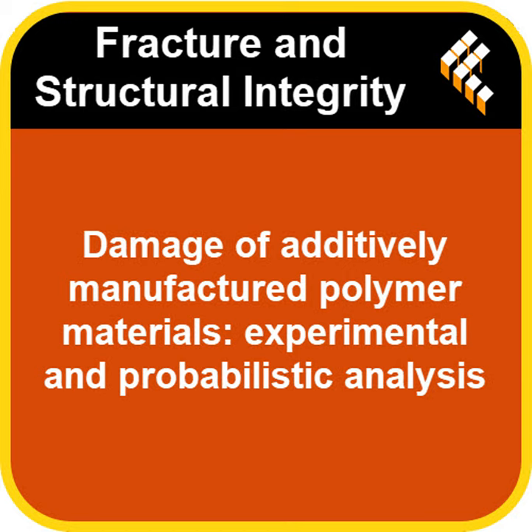And this study's results on PLA really drive that home. They tested orientations at 0 degrees, 45 degrees, and 90 degrees relative to the pulling force. And the difference was stark. Really stark. The 0-degree orientation, where the filament lines run parallel to the pull, along the direction of the force, showed the highest tensile strength. It took the most force to break it. While the 90-degree orientation, with the filament lines perpendicular to the force, so the force is trying to pull the layers apart. Exactly. That was the weakest by a significant margin.